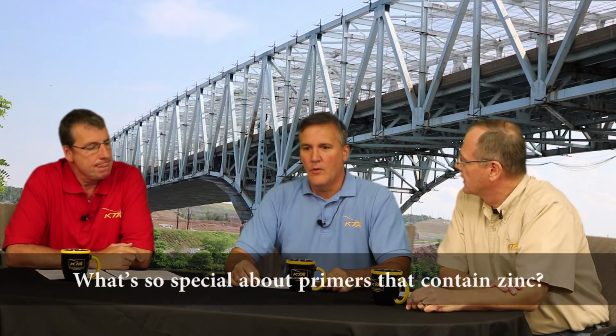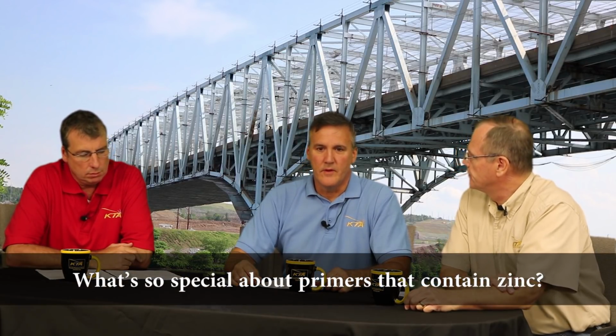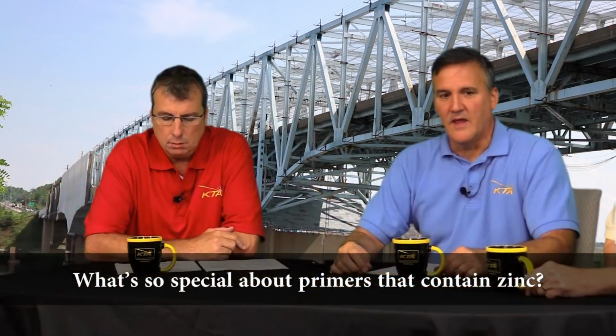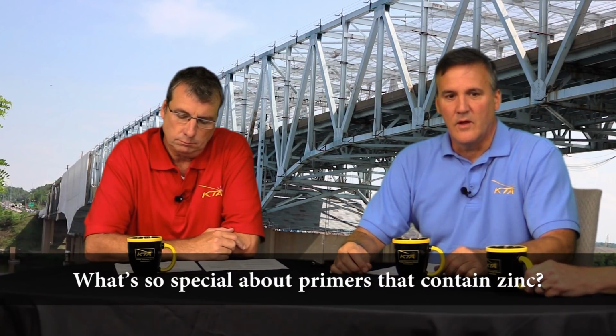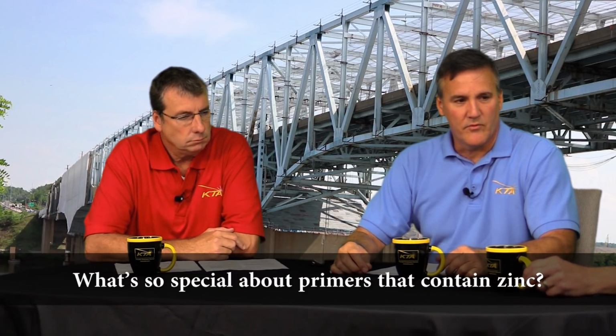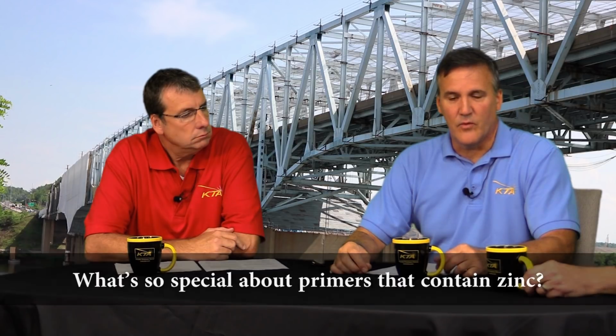What is so special about primers that contain zinc? Well, similar to hot dip galvanizing and zinc metallizing, organic and inorganic zinc primers provide a zinc-rich coating that provides galvanic protection or sacrificial protection. It sacrifices itself to protect the steel, and that's the reason why it's very important in the corrosion protection process. Okay, so in addition to barrier protection, it gives you this galvanic type protection.